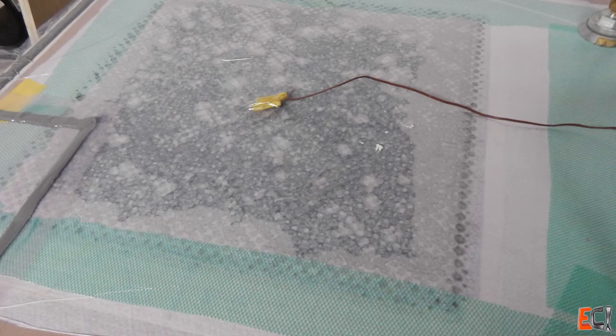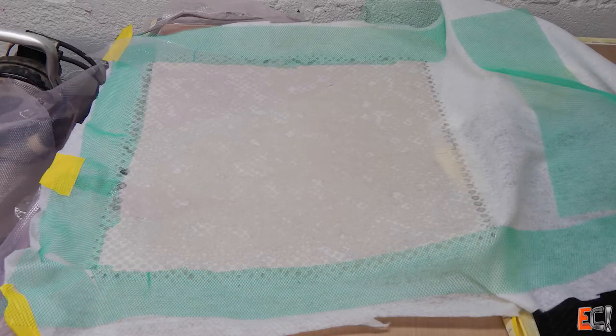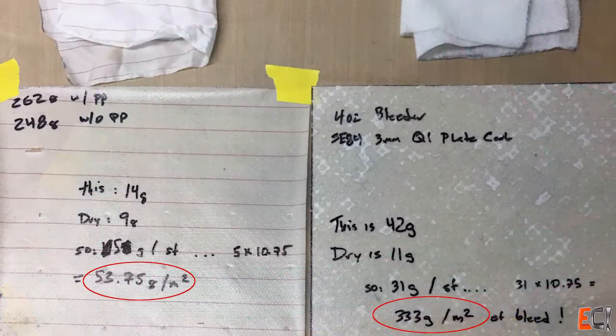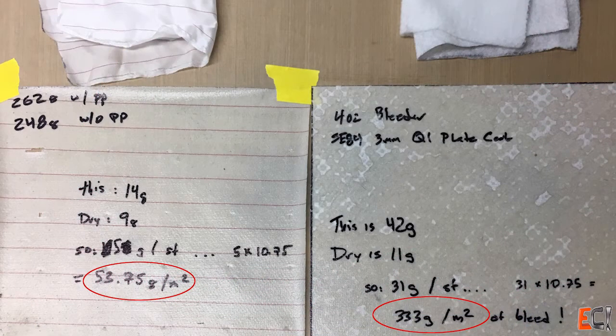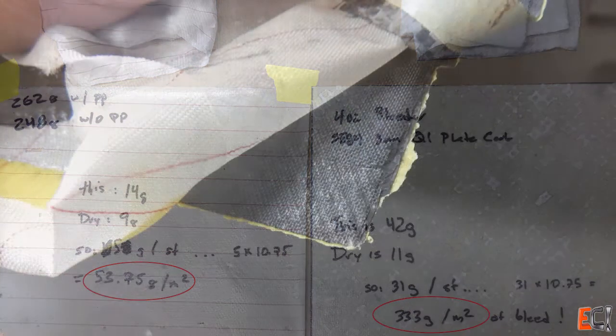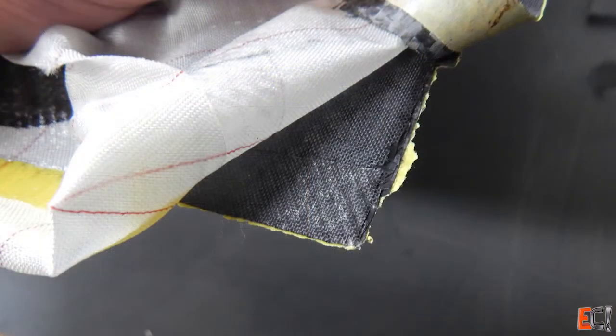Turns out I had a lot of bleed almost completely saturated the breather. This is not great because this resin should ideally remain in the laminate. So I took it off and cut a square of bleeder and peel ply and it turns out I was pulling off 330 grams or so of resin which is an awful lot. That resin should have been in the laminate but it did come out nice and flat.